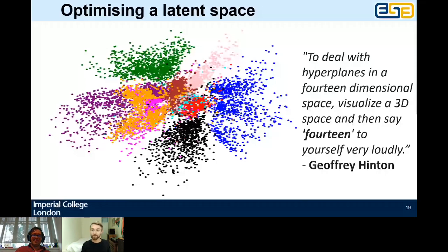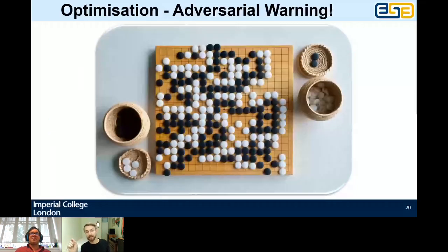There is a warning for myself and for all of us, which is that if you start trying to do optimizations based on simulations, you can end up with silly results. And the results will be absolutely correct if you've got the maths right, based on the simplifications that you've made in your electrochemical model. So, a good example would be that in many battery models, we ignore electrons. We just assume that they can get wherever they need to be.